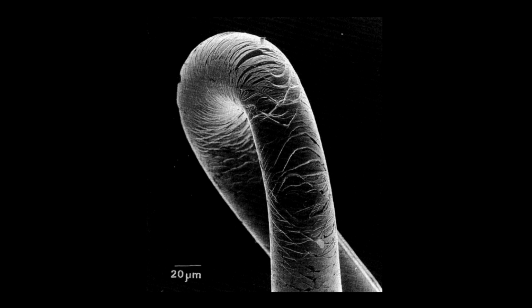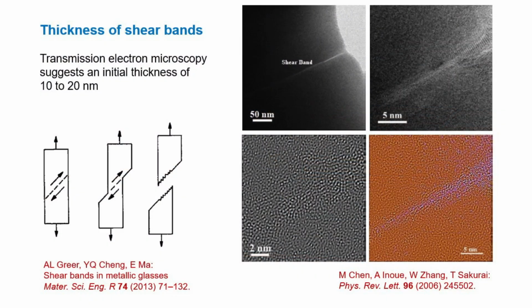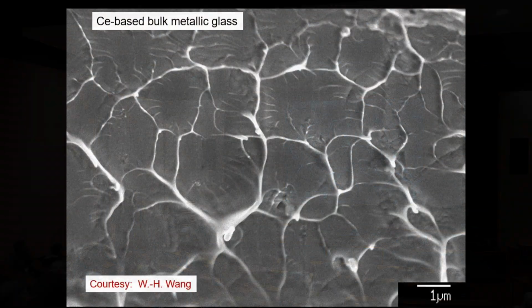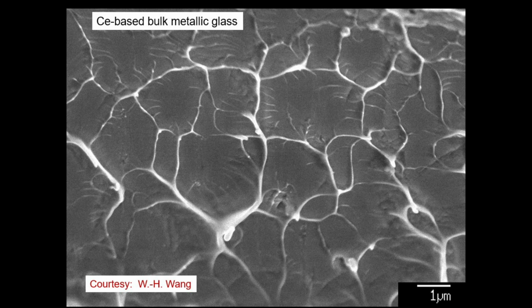If you were making some component, you wouldn't want to have these surface markings on it. Of course, when this bar was bent, it was then allowed to spring back. And here's a little bit that obviously lived between two shear bands, and when it was springing back, popped out, which is saying that the bits of metal could slide extremely easily relative to each other. The actual width of a shear band from microscopy is taken to be about 10 to 20 nanometers, and that probably applies in the early stages. Then you get to something like this, and then the thing comes apart. The fracture surface is quite remarkable. It's this so-called vein pattern, which I can now reproduce for you, I think. I'll give myself a black background.